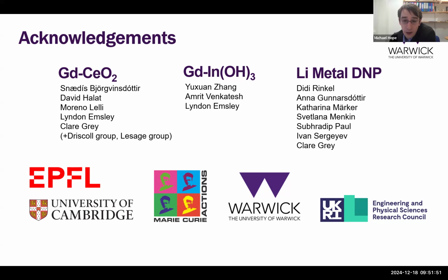Of course, that doesn't rule out any direct contribution that could be there, but we know from the sign of the DNP that it's dominated by Fermi contact. Overhauser DNP with a positive enhancement means that we're dominated by Fermi contact, and you're not going to get significant Fermi contact between the metal and diamagnetic species in the salts. At least off the top of my head, that's what I would say.